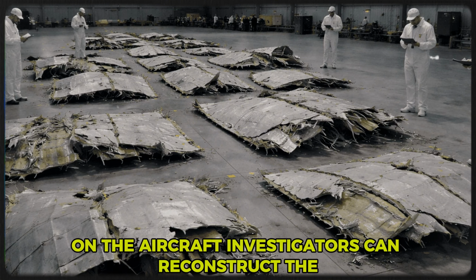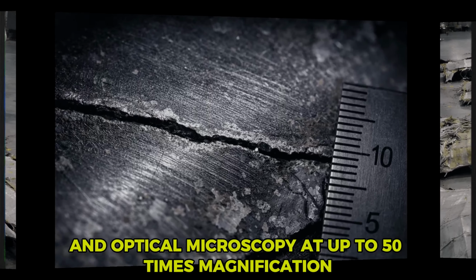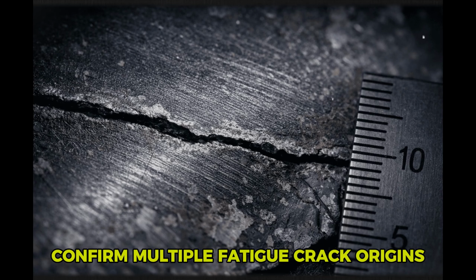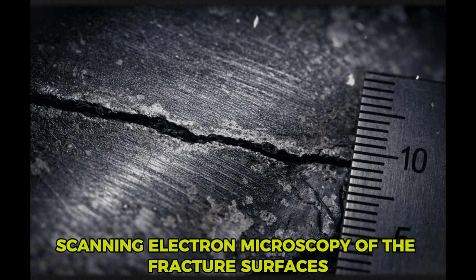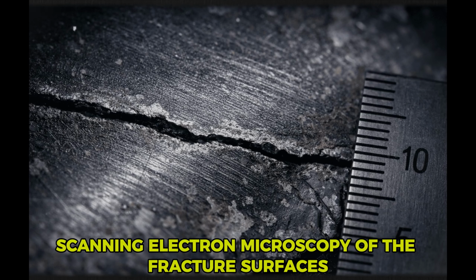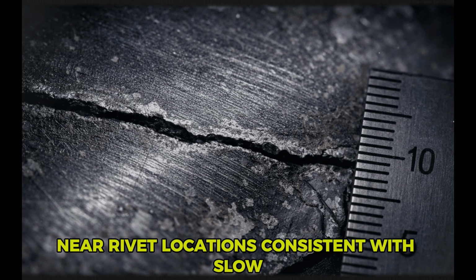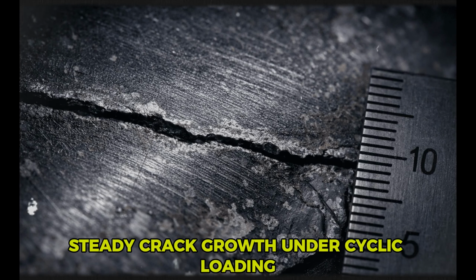The key physical evidence came from recovered sections of the aft fuselage skin near Body Station 2100 between stringers S48L and S49L. This was the location of the 1980 tail strike repair. Examination revealed flat fracture surfaces along the edge of the external repair doubler. Penetrant inspections and optical microscopy at up to 50 times magnification confirmed multiple fatigue crack origins on the skin faying surface. Scanning electron microscopy of the fracture surfaces revealed fatigue striations with spacing of approximately 2 microns near rivet locations, consistent with slow, steady crack growth under cyclic loading.